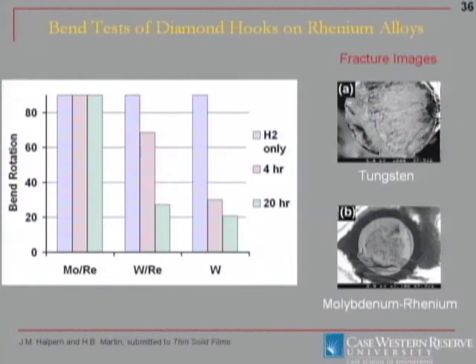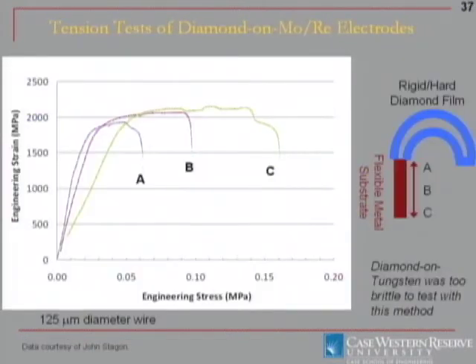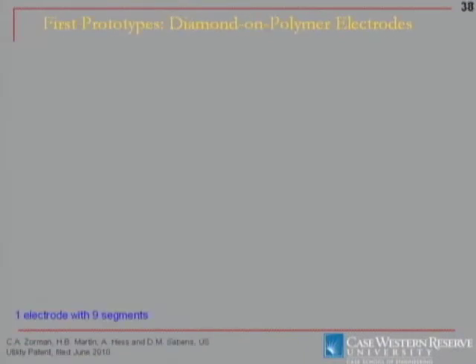And that goes back to the microstructure of why this works. The tungsten gets completely carburized. This is a brittle phase. Here shows a very ductile core of the molybdenum-rhenium with a slight brittle phase on the outside. And again, this is an alloy, so the molybdenum may still form a carbide. Tungsten-rhenium looks similar to this, but probably more carbide, because the tungsten is better at doing that. I'll skip this. This is the idea. We're also doing tension tests to do more mechanical testing.